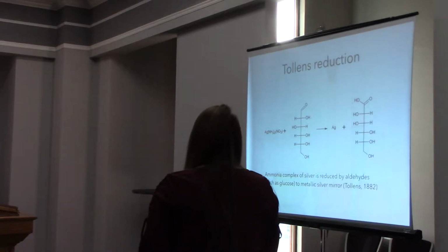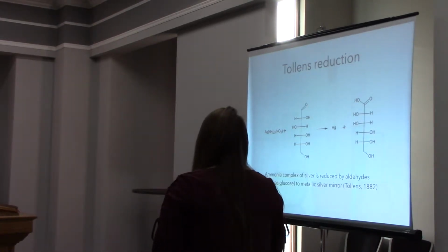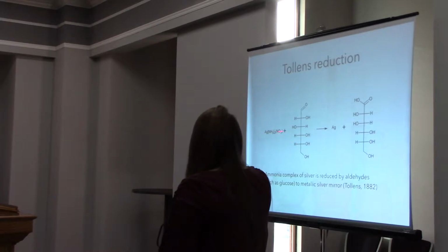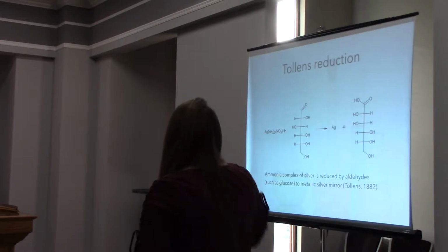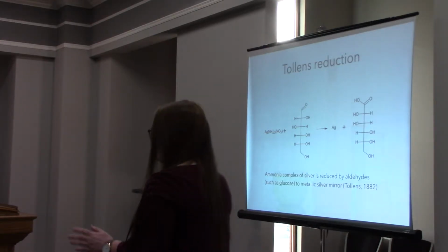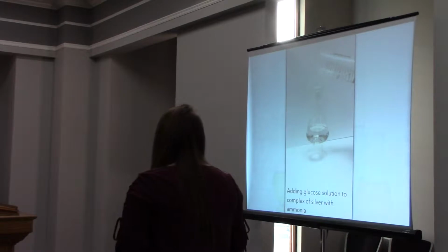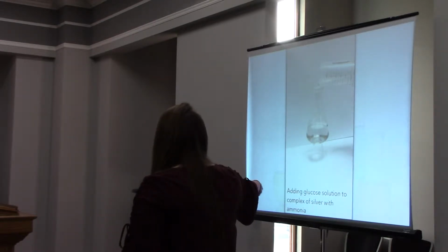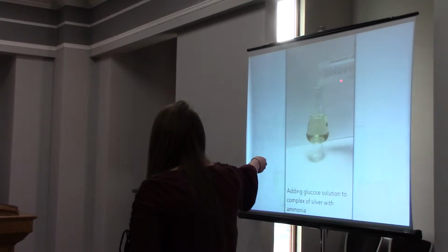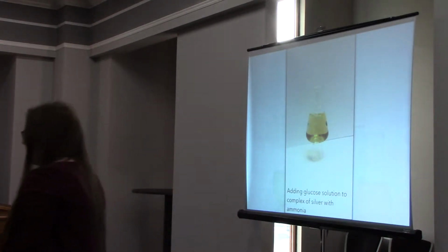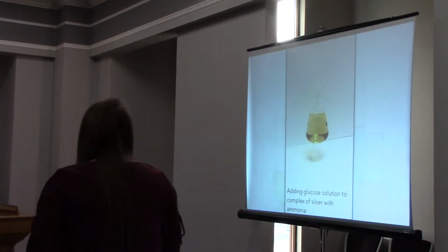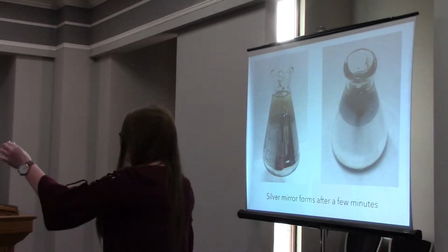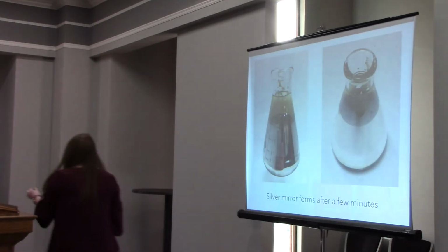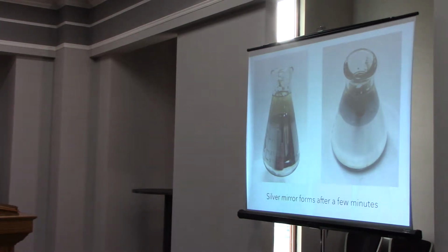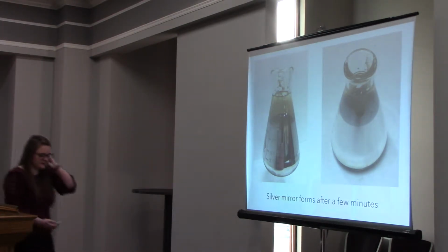Here's the Tollens reduction reaction. You can see the ammonia complex of silver, and then this glucose aldehyde is reducing it to a metallic silver mirror. So here, this is the complex of silver and ammonia, and we're adding the glucose solution to it, and it turns this amber color. And then after it sits there for a couple minutes, it turns into this silver mirror. Here, I'll pass this around so you can see it. It turns this silver mirror that kind of coats the inside of the flask.